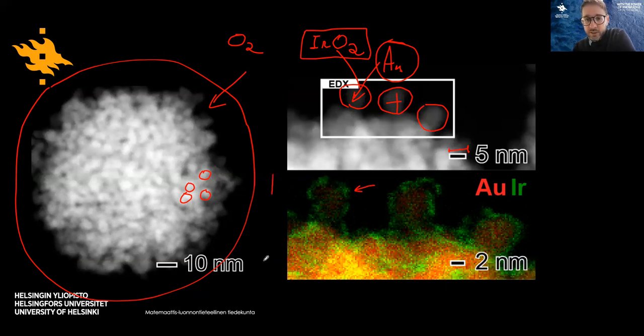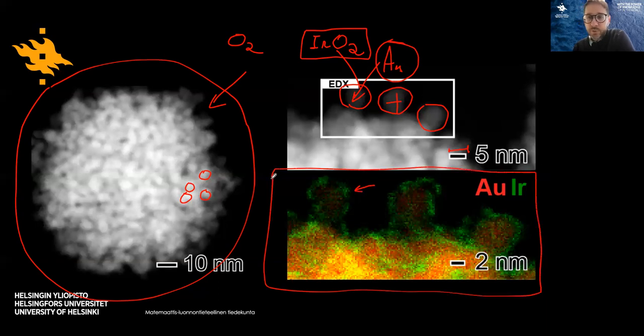And actually, in this image, we can see a compositional map also performed in a transmission electron microscope in scanning operating mode, in which we can determine the exact locations of gold and iridium in the nanoparticle. Gold is represented here by the red color, and iridium is represented by the green color. And then we can see this kind of morphology in which iridium is concentrated at the surface.